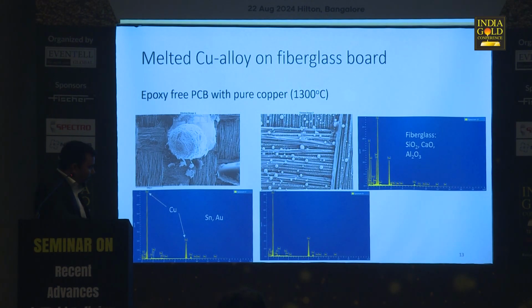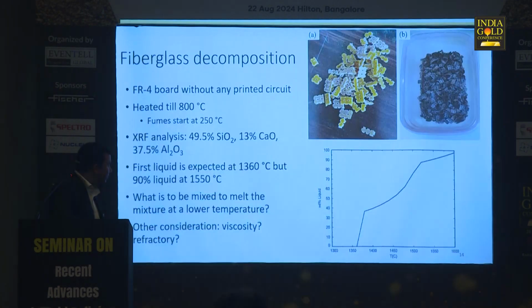Okay, so I presented this as one slide, but this was one year of work for one master's student. Then we started looking at this fiberglass in a little more detail, what it is. So we bought just the FR4 sheets without any electronics. And then we roasted it at 800 Celsius so that we get rid of any plastic if it is there. We get this, which can now be crushed. So then we crush it, sample it, and send it for chemical analysis. It comes out about 50% silica, about 13% calcium oxide, and 37.5% alumina.